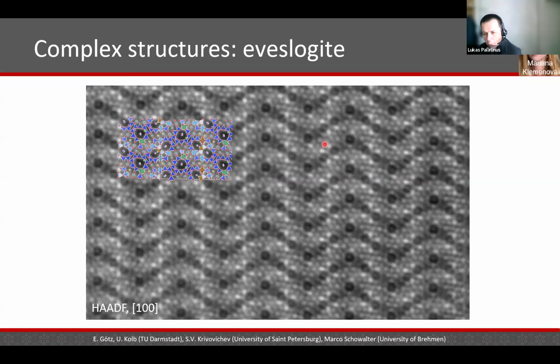I think this is only emerging right now. I'm not aware of any electron diffraction studies under potential, for example, but there are, of course, temperature-dependent studies, which are relatively easy to do in a range of temperatures. There are sample holders which allow you to reach from, say, liquid nitrogen temperature all the way up to 800 degrees centigrade routinely, even more sometimes. So temperature-dependent studies are possible, and definitely also studies under electric field would be possible, or even there are also people trying to go into the time-resolved area. So then pump probe experiments would also be possible.